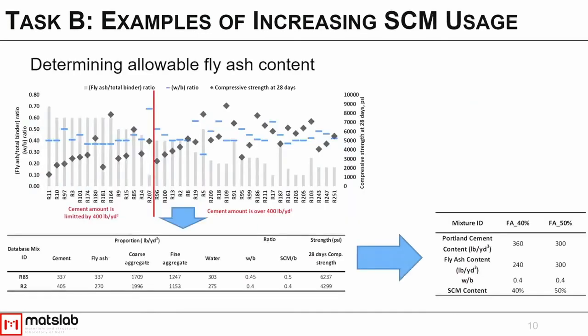So when we were looking to create these mixture designs, we went through a process of a literature review, which we basically pulled out many different mixture designs from literature based around a certain topic. So these are all mixture designs that have fly ash. They're rated by the compressive strength at 28 days. We were looking for a system that had 4,000 to 5,000 PSI at least. The water to cement ratio, we wanted at least systems that had around a 0.4 water to cement ratio. And then we wanted total Portland cement content to be less than 400 pounds per cubic yard.